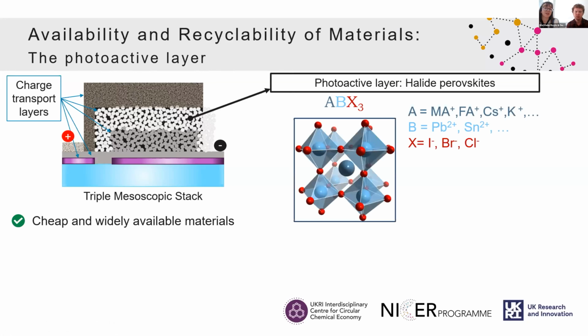We chose them because they're cheap. They're made of widely available materials. We can look here. This is the structure of a perovskite. They are ionic crystals with an ABX3 structure. So you have either iodide, bromide, chloride in the red dots. Then forming a cube, you have normally a metal that is predominantly lead, but it could be tin. And then in the center, you have either organic cations like methylammonium, formamidinium, or other inorganic elements like cesium, potassium, etc.